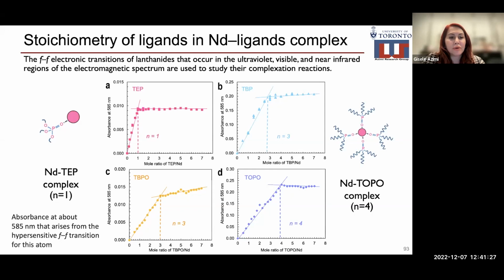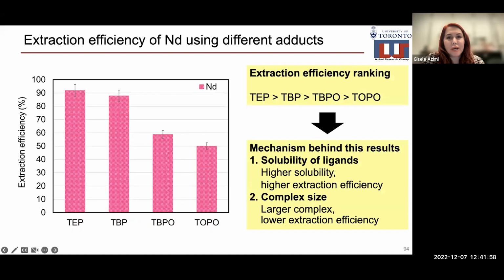And this absorbance at this wavelength arises from the hypersensitive f-f transition of this atom. You see that the absorption increases by increasing the ligand to neodymium ratio, and after a certain point, it reaches a plateau. The point that these 2 lines cross each other is the number of the ligand. So for TEP, we have 1, TBP, we have 3, TBPO, we have 3, and TOPO, we have 4 in the complex. We use these 4 ligands and we performed extraction efficiency.